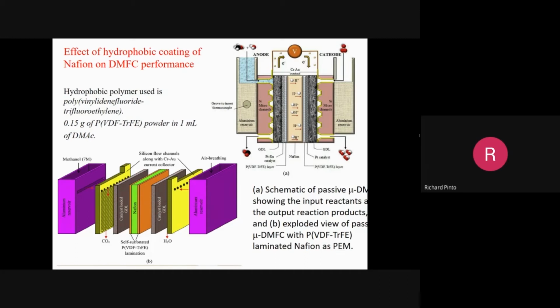Current depends upon the internal resistance of the device. That's like a battery: the lower the internal resistance, the higher the current you can draw. So the internal resistance of the membrane is very important. If you use a very thick membrane, then you have a large internal resistance, so the power output drawn will be less. At the same time, if you use a thin membrane to increase the power density, then methanol crossover will be large. So you have a trade-off. You need an optimum balance between thick and thin membrane.